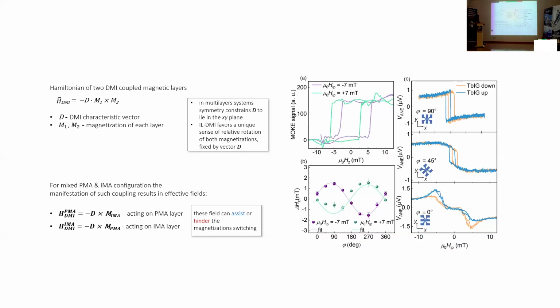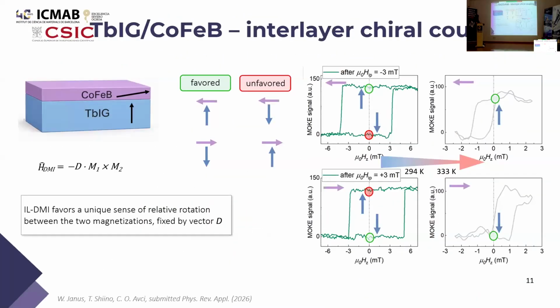Well, if you look at the loop, it's shifted, right? So due to this shift, since now I should go back to here. Here the loop is also shifted, but if we increase the temperature, you can see that the entire loop is shifted. So this means that this internal field in our sample, which is due to the chiral coupling between the two layers, suppresses the coercivity of our loop. And this is why only one state is possible at this temperature. Okay, I hope that helps.